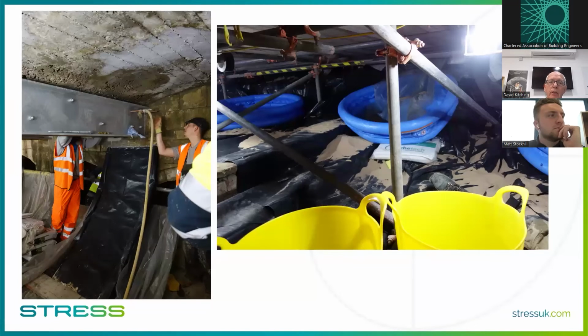But if you remember that cross section, there was concrete on the outside, two steel beams, and then a void in the middle, because that's the real problem: the Victorians didn't completely seal those steels in. So we still had a void there. So although the new steels are actually going to take the full load of York Street and can do, it's silly to leave something there that potentially can corrode with time. And so, in fact, we'd already allowed to grout up that void and have holes put in the new beams, so that we can actually get through into that centre area and grout it up.